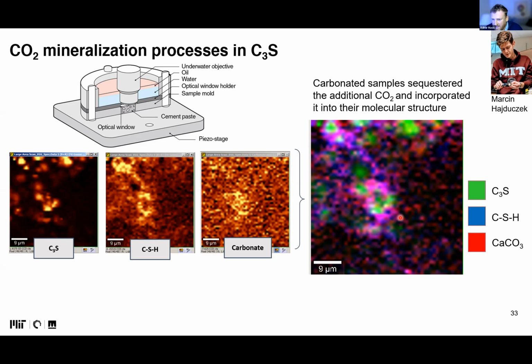And I think here we are opening an incredible opportunity for investigating clear microscale reactivity of CO2 in a complex cementitious material, because now you could imagine that while C3S is hydrating, it will produce CSH, but also calcium hydroxide. Calcium hydroxide will interact with CO2. Where is it interacting, at which stage, which phases are involved?